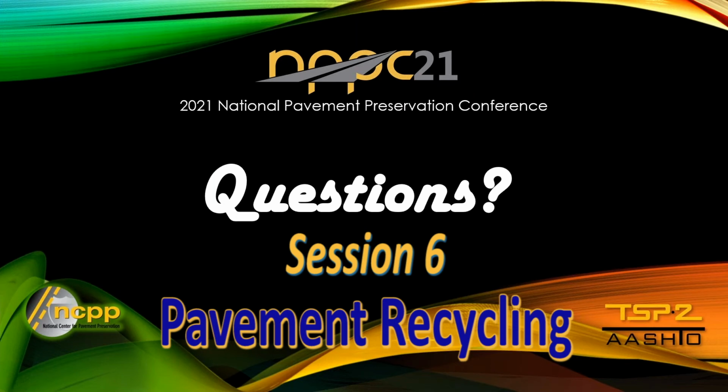Next question is, what does corrective aggregates do? A lot of times what corrective aggregates can do, you can bring in some extra material, some maybe more angular, some more stronger material to act as more of a load-bearing portion of your CIR mixture. Can correct gradation a little bit if you have a gap gradation. For example, if you have an open graded cold mix and then layers of chip seal, you might add something a little more dense graded in there to help lock up the uniformity of that mix, because now it's going to be a dense graded structural bearing layer.